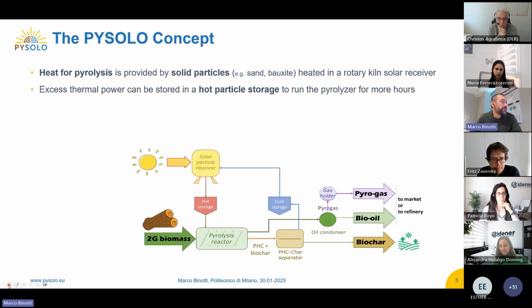So the basic concept of the PYSOLO project is to provide the heat for the pyrolysis via concentrating solar power. To move the heat from the receiver to the pyrolyzer, we use a particle heat carrier. This is a common practice in pyrolysis reactors, where for example sand is used. So the idea is to use the very same sand as a heat carrier in the solar receiver. Of course, coupling the pyrolysis reactor with CSP also allows a storage system to be integrated, in order to increase the number of operational hours of the system.